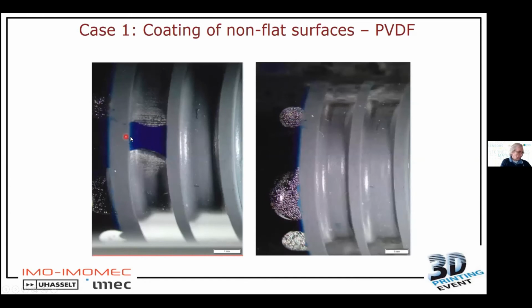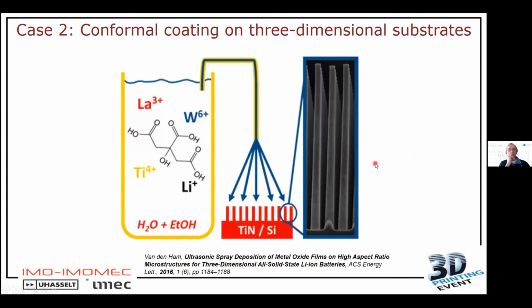And also, this is the result where you see some liquid flowing into the pores, if you have a coating on top or not. And another option is, of course, because of this vortex that we create, the option to coat selectively only the pillars that you see here. So you don't fill up like we did with the ultrasonic spray coating on 3D printed parts. Here we would like to have a coating only on the pillars without filling it completely.